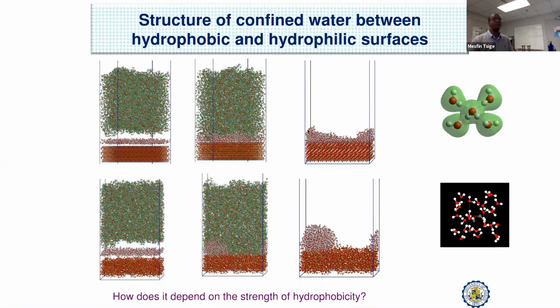And this hemispherical cup would pretty much increase in size if I go from a bilayer to a trilayer. So we only have one stable layer, but the rest will form a hemispherical cup. When we replaced the quartz with amorphous silica, which is what's commonly used for purifying water, in that case, we have a small number of OH groups on the surface. Here I say 9.6. When we come to amorphous silica, I have about half or less, 4.1 to 4.3. So as a result, we have reduced the hydrophilicity of the surface.